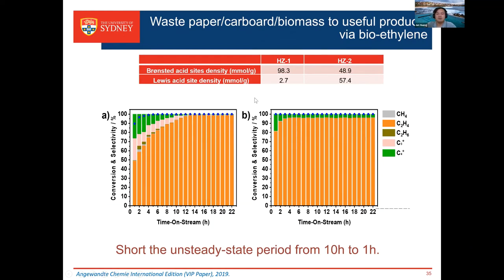But the main challenge for this kind of process is a longer induction period for conversion. Recently we developed a new catalyst, which shortened it from previously 10 hours to only half an hour to an hour. Then we are able to make it easier for commercialization.